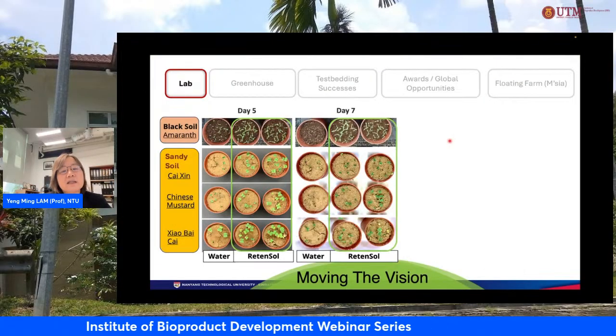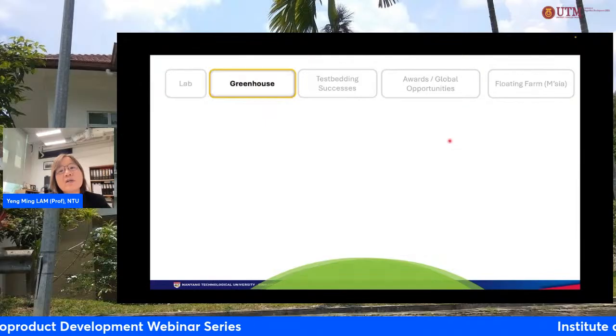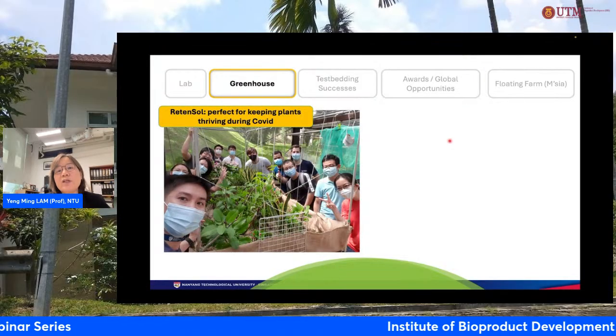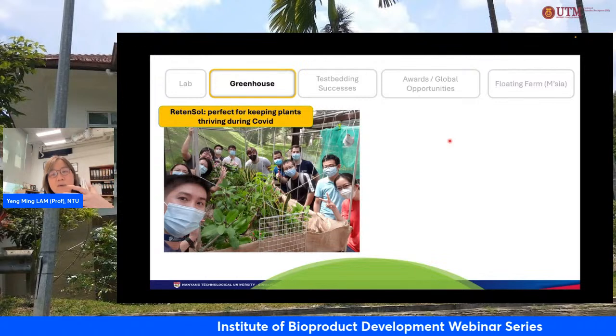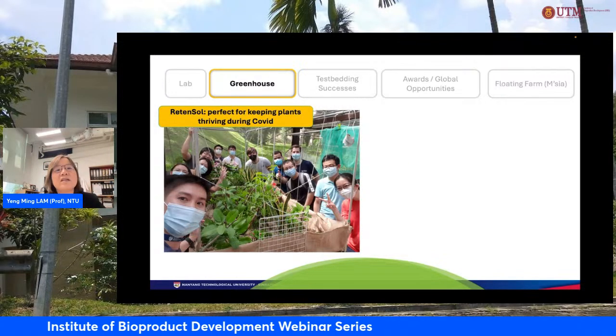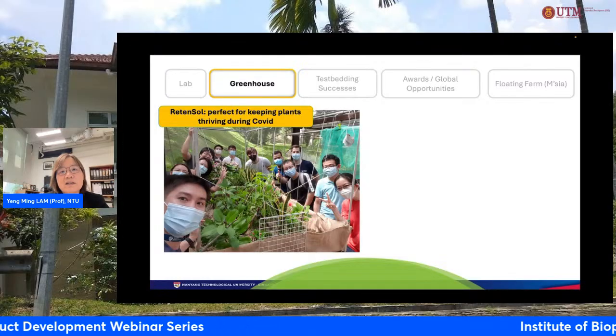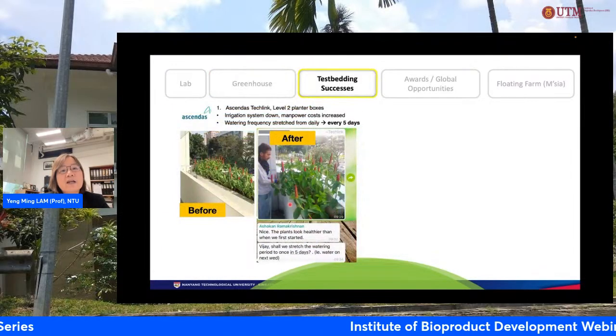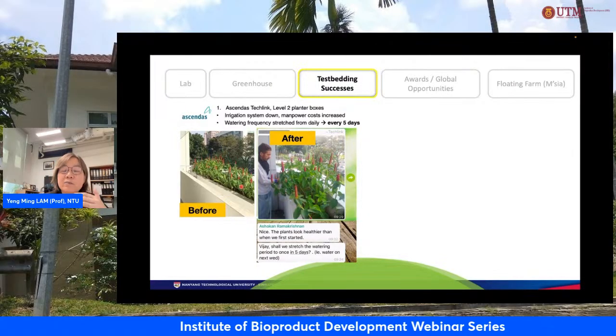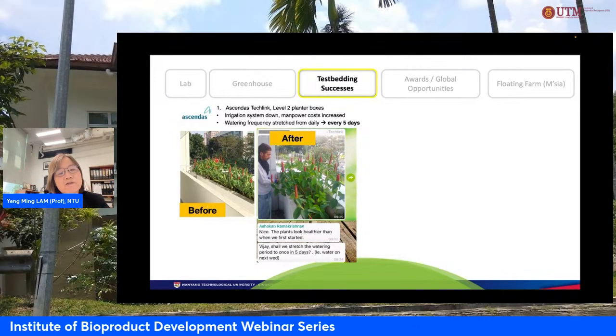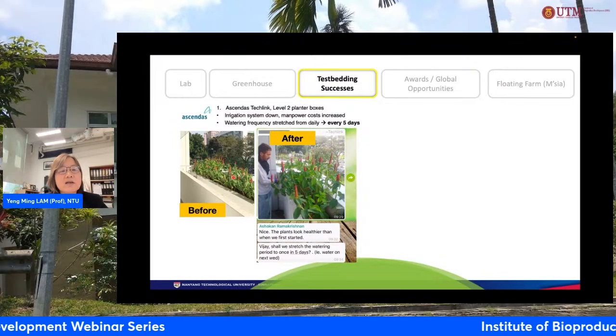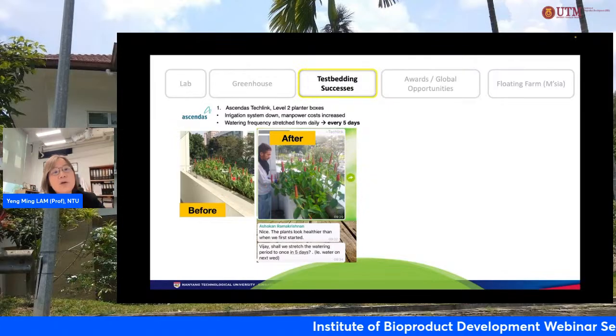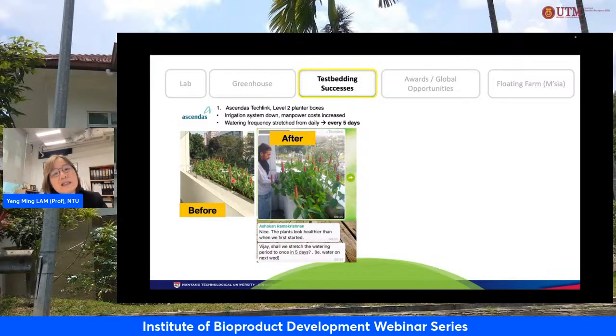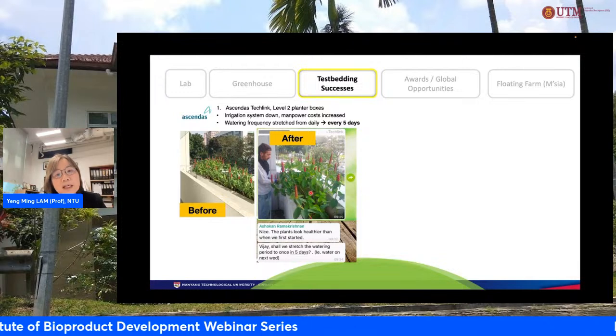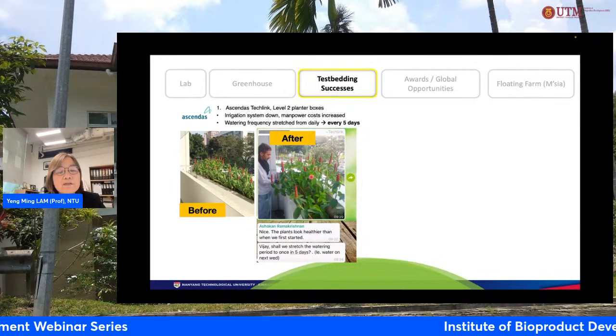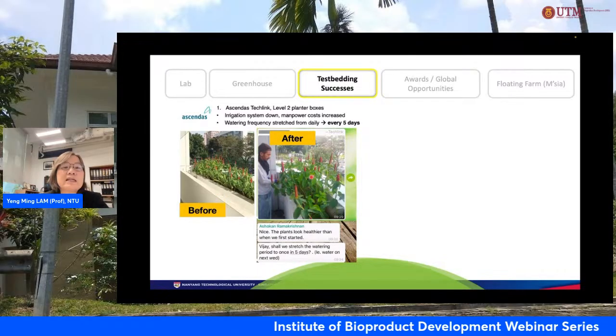So we have tested it in small plant pots in small greenhouse. We have also tried in large greenhouse where we do it over COVID because the students and all my staff left it to grow for over a period of time. With RetenSol, it was able to keep the plant survival rate very, very high. We also test it in one of the building site, which is an industry building block, where they have greeneries. And with the greeneries, we started off, they actually have to do watering every day, but because of the usage of RetenSol, they now can leave the plant with no watering for 3 days. And then in fact, we were able to stretch it for 5 days. So this actually helps to reduce the amount of water that's required for these plants.